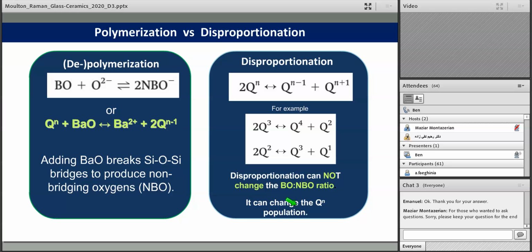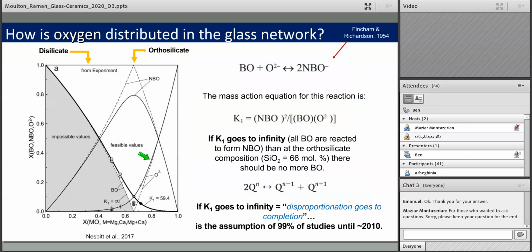Contrast this with depolymerization. If you have pure silica and you add barium oxide to it, the free oxygen here from the barium reacts with the bridging oxygen on the Qn species to create 2 non-bridging oxygens, and you have this barium sitting in your network. So adding any metal oxide breaks up the connectivity of the silica tetrahedron. And we're going to look at how these two situations relate to one another. So let's define that a little bit more explicitly.